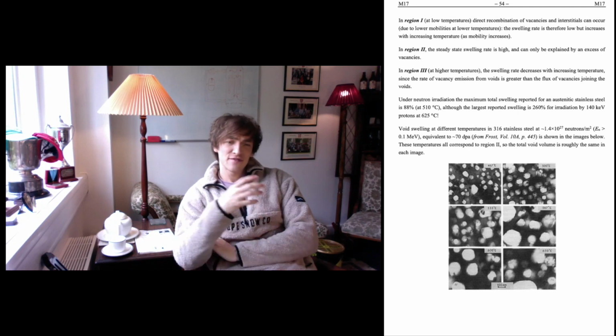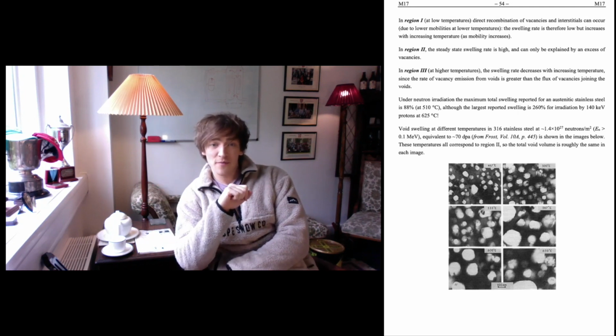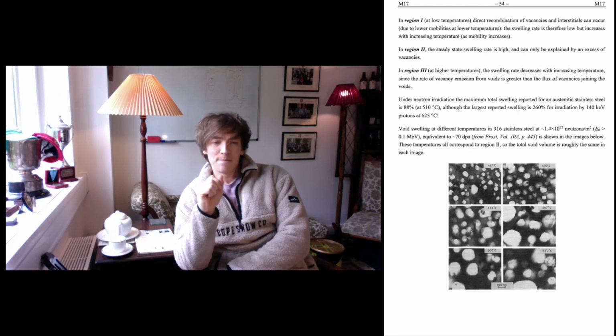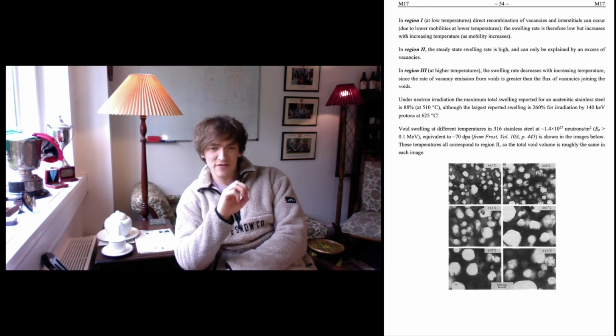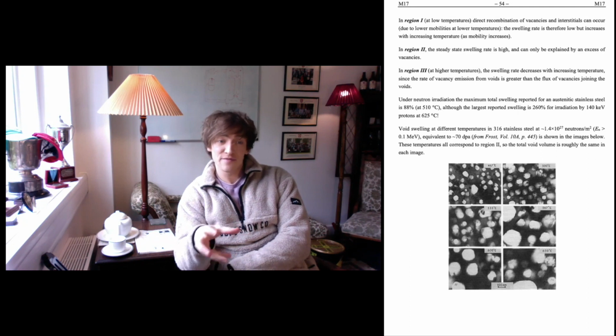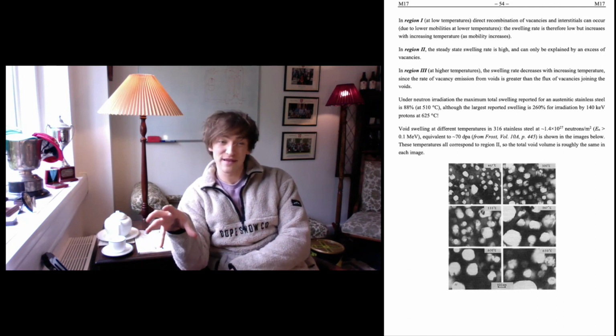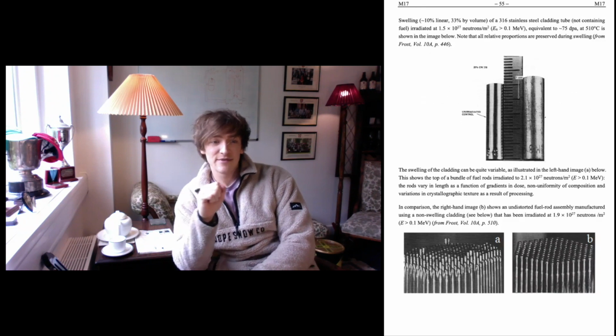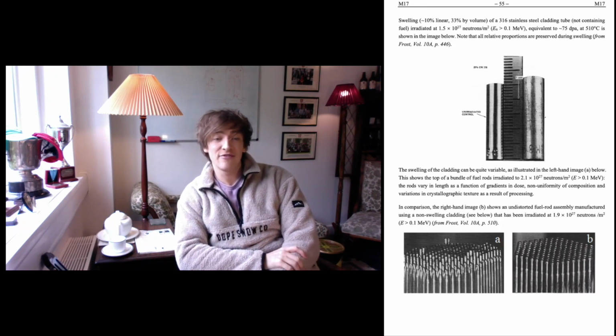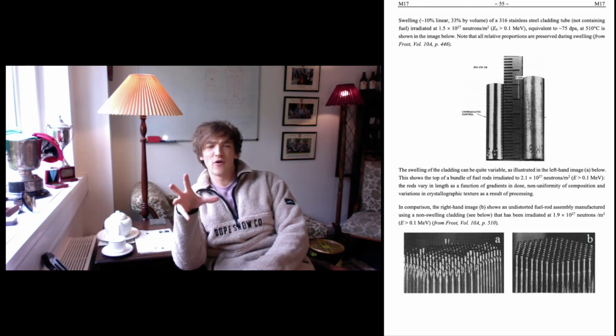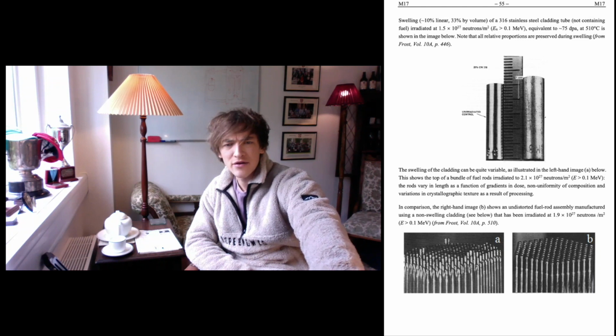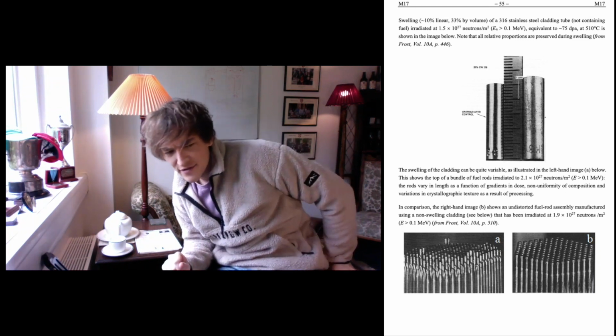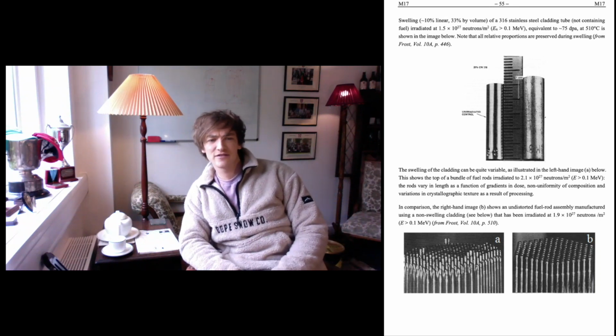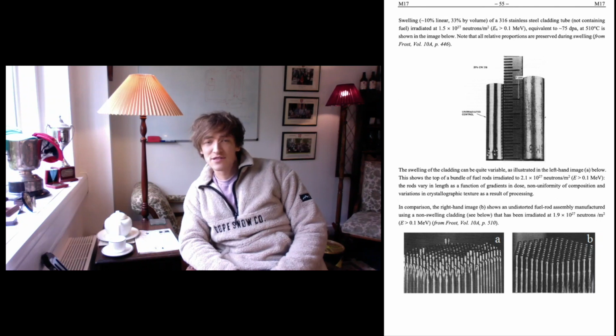And that degree of swelling as a function of temperature is shown in these micrographs on page 54 at the bottom of the page there, with very large voids forming at 650 degrees Celsius compared to the smaller ones at lower temperatures, which makes sense with what I've just described about our different regions and our temperature dependence. And should you wish to see the effects of swelling on a macro scale, here is an image of an unirradiated stainless steel rod versus an irradiated one, indicating the sort of increase in volume. This rod in particular was irradiated to 33% swelling by neutron irradiation. That's equivalent to about 75 displacements per atom at 510 degrees Celsius. And as you can see, all relative proportions have been preserved.